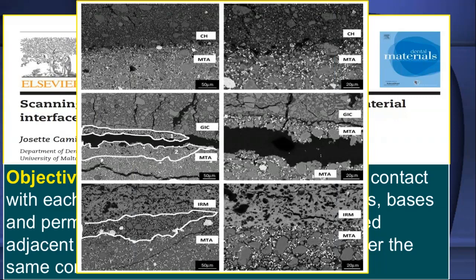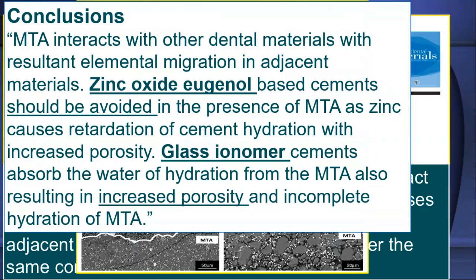That was fine. But when she put a glass ionomer on top, it was not good. It was a really bad thing. And the same thing with IRM on top of MTA. And there's people who teach that. But you have to read the literature. And this is a quote from the article: zinc oxide eugenol-based cement should be avoided in the presence of MTA, and glass ionomer cements should be avoided because they increase the porosity and they cause incomplete hydration of the MTA. So they're really not a good idea.